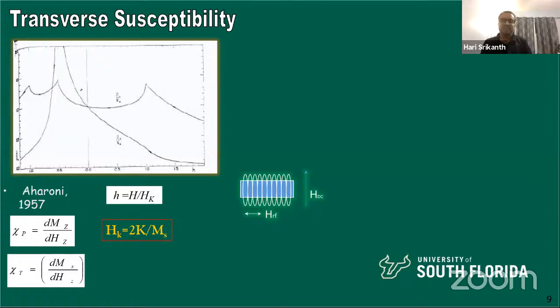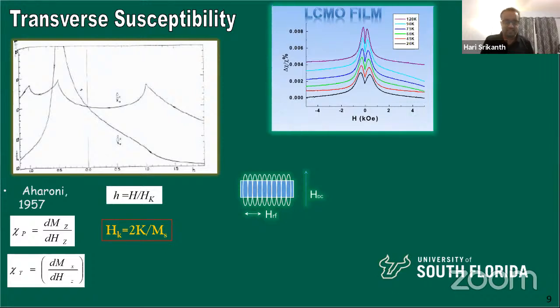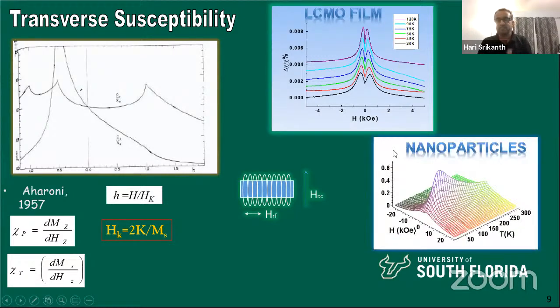Okay, so that's why our experiment became quite popular in measuring anisotropy, because yes, we can detect these peaks. These are the Aharoni peaks that he theoretically predicted, and we can measure this with our data that I showed you using the experiment. We can follow that as a function of field, and we can do it at different temperatures. So we can get an entire phase diagram in the HT plane for nanoparticles.